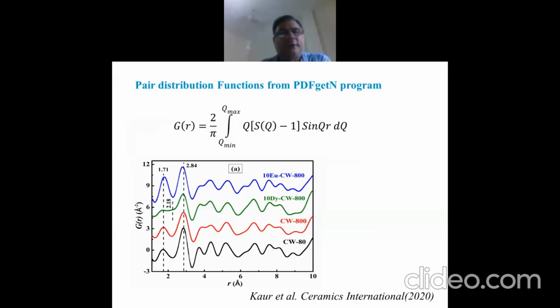We also carried out neutron diffraction studies at the Bhabha Atomic Research Center in Mumbai, and also some measurements were done at Budapest Neutron Center. The resolution of the neutron spectrometer is less as compared to the resolution of an XRD system, so the peaks are broader, but the result is the same, that the materials are two-phase materials. We calculate the pair distribution functions from the Fourier transform of the structure factors, and the peaks in the pair distribution functions G(r) give you the probability of finding the atoms at a particular distance from a reference position.